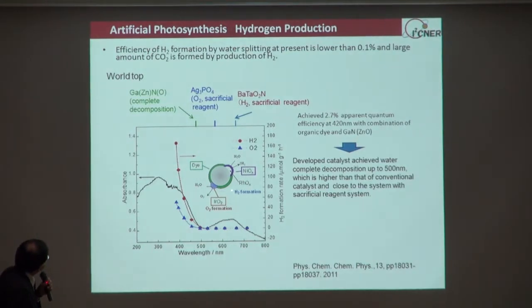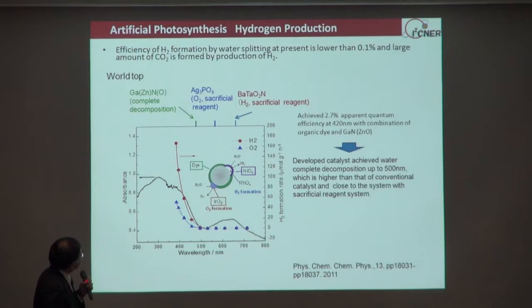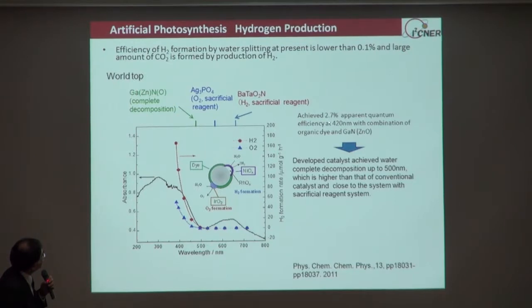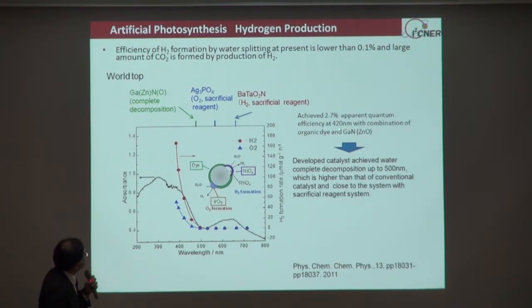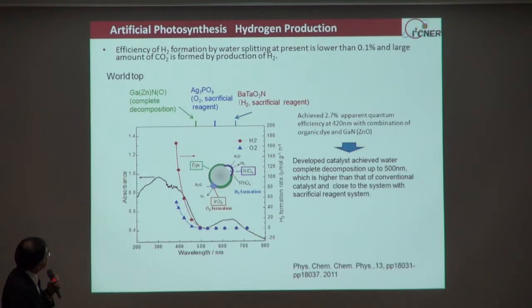And then we started to find a new inorganic catalyst which uses visible light for the excitations. And this result was also introduced by Director Sophronis. But as you can see here, by using zinc oxide doped gallium nitride, we can use light up to 500 nanometers. And then the conversion level is 2.7% apparent quantum efficiency at 420 nanometer light. And this was much improved over the previous KTaO3 systems.